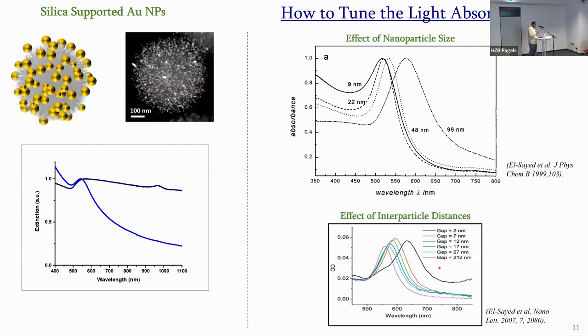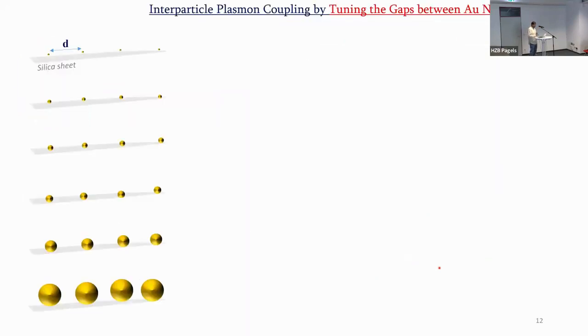Now the question is, how do we tune the distances between the particles? You can tune the size, you can tune the shape, morphology, but how do I tune the distances between the particles so that I can have a different plasmonic coupling? So we came up with this idea that, okay, consider this as the silica sheet of that entire DFNS particle. For simplicity, I'm just showing one sheet. And then we loaded gold nanoparticles at certain distances. This is possible by amine functionalization.